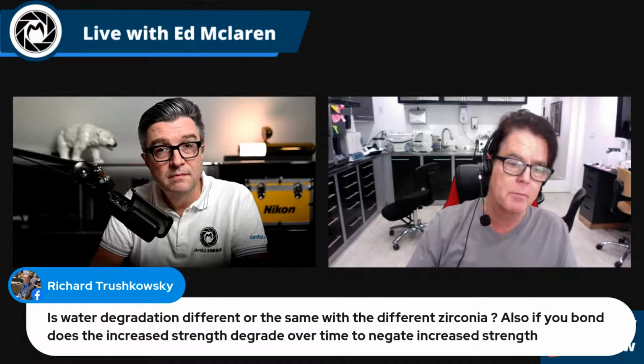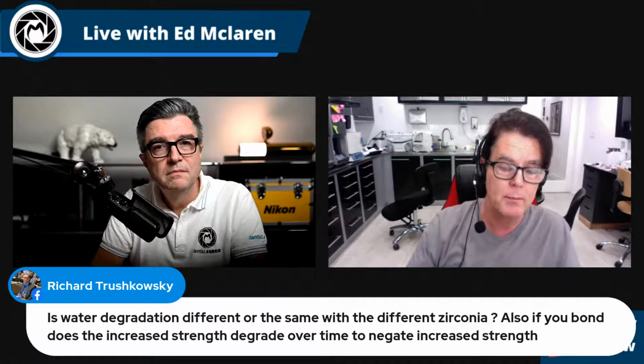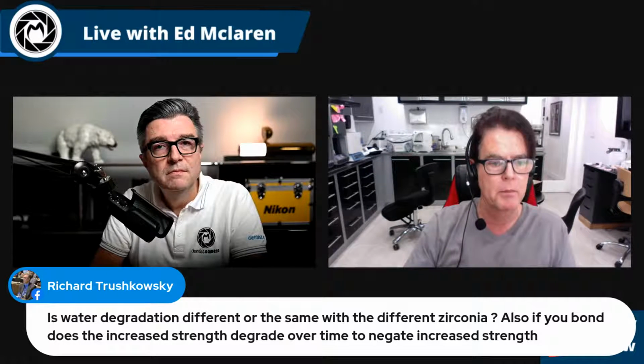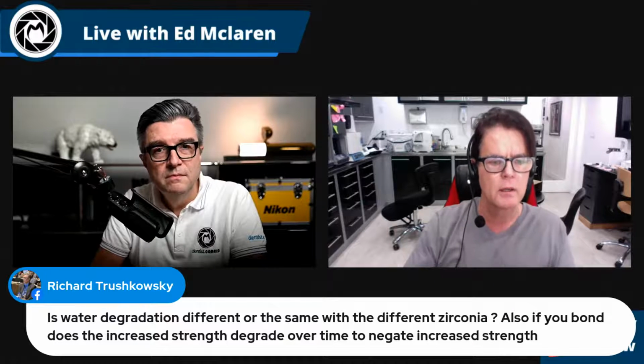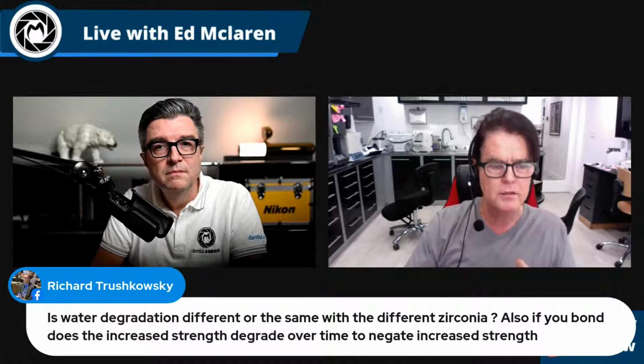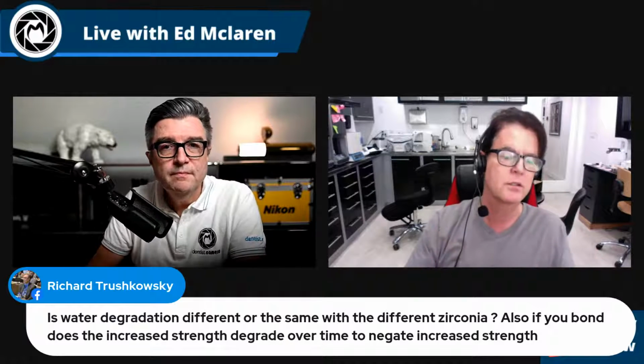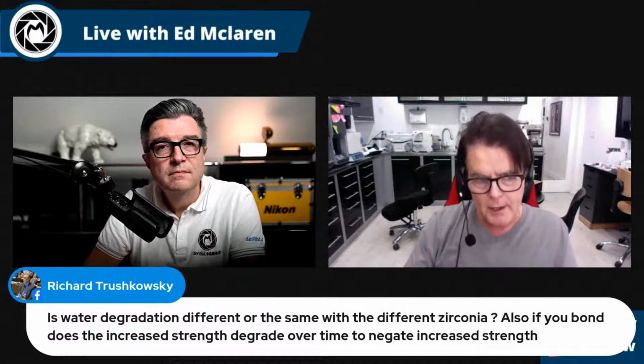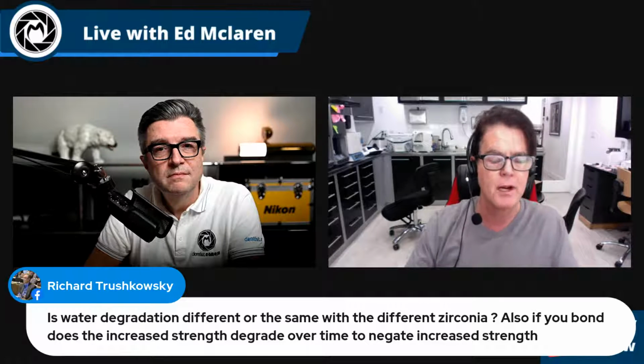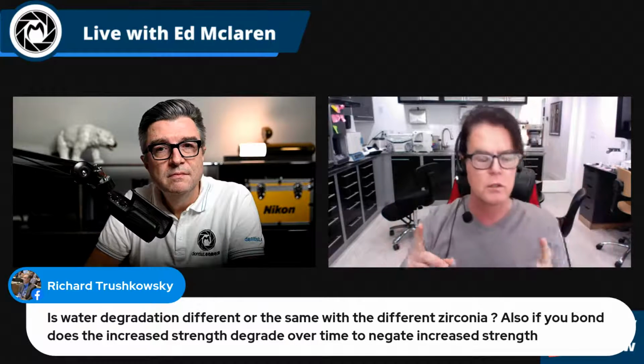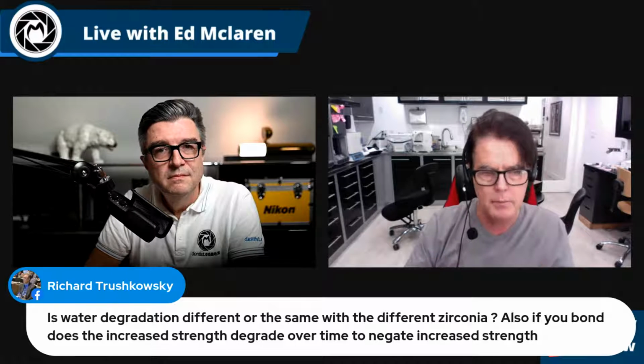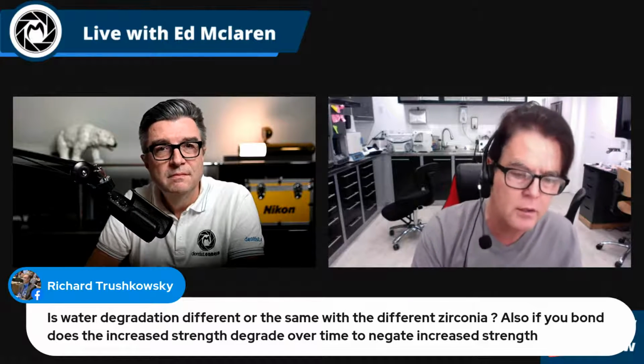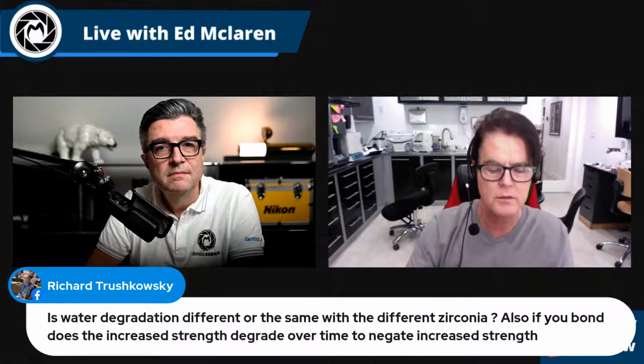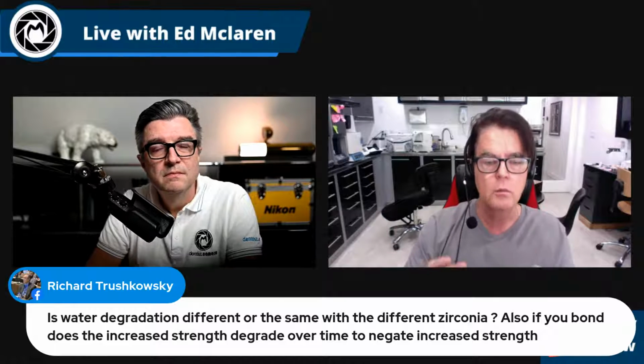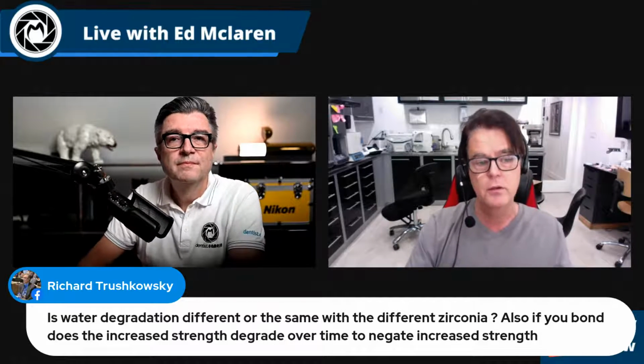So if you do a fast sintering, maybe one of the things to take from that paper, if you're doing a fast sintering with a 3Y or maybe even a 4Y, I would bond that to the tooth, even though you don't think you need to do it. I'd put an MDP primer on the inside and some resin cement so that I'm protecting that surface from moisture. Because if we go back to my salient point about fracture, the fracture starts from the inside of the crown and works to the surface. That's well documented. Bob Kelly did a lot of work, and Matthias Kern did work on the fracture patterns of zirconia and alumina, by the way. So let's protect that surface for sure if we're going to do fast sintering.